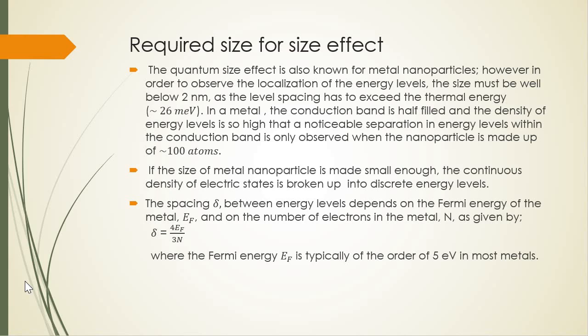If the size of a metal nanoparticle is made small enough, the continuous density of electronic states is broken up into discrete energy levels. The spacing delta between energy levels depends on the Fermi energy of the metal, EF, and on the number of electrons in the metal, N. This is given by delta equals 4EF divided by 3N, where the Fermi energy EF is typically of the order of 5 electron volts in most metals. The discrete electronic energy levels in metal nanoparticles have been observed in far infrared absorption measurements of gold nanoparticles.